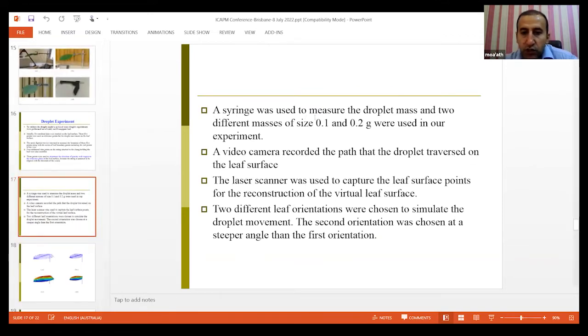Then a syringe was used to measure the droplet mass and the different mass sizes. We selected 0.1 and 0.2 gram for use in our experiment. A video camera recorded the path that the droplet traversed on the leaf surface. A laser scanner was also used to capture the leaf surface points for the reconstruction of the virtual leaf surface. And finally, two different leaf orientations were chosen to simulate the droplet movement. The second orientation was chosen to be a steeper angle than the first orientation.